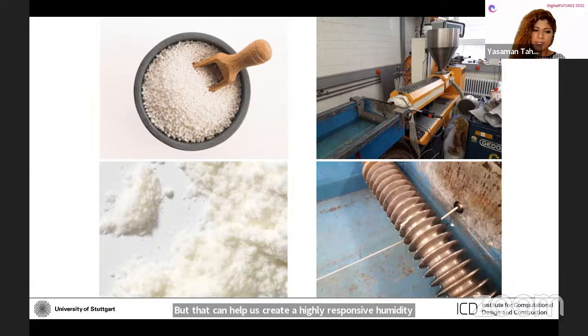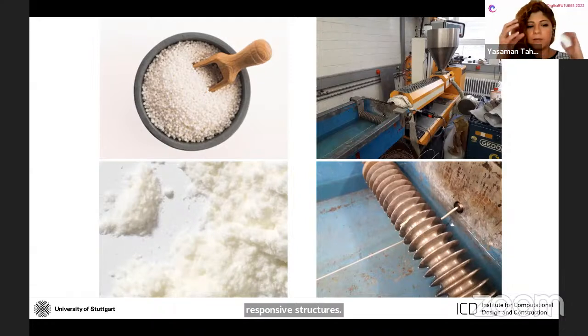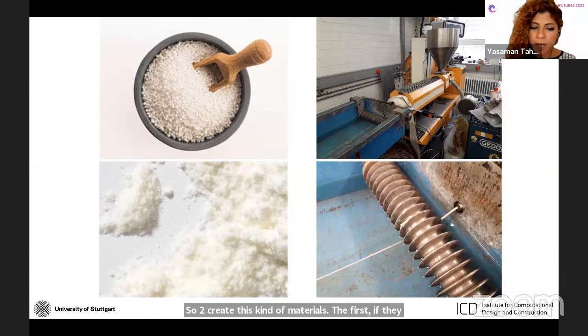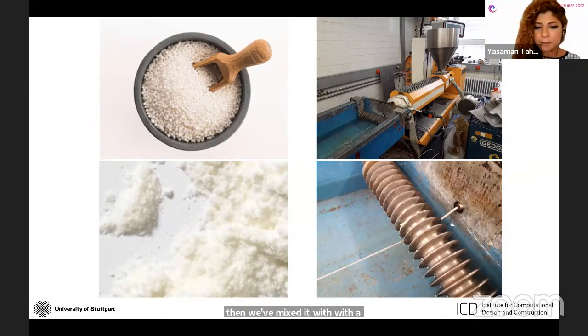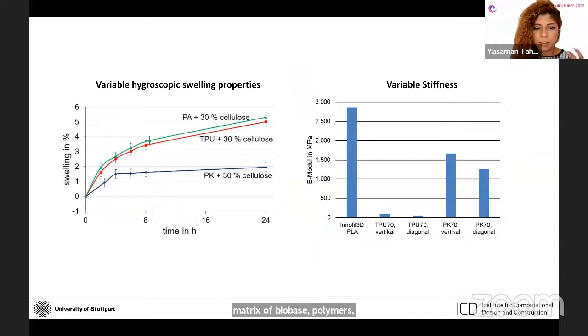So to create these kinds of materials, we looked at the basic elements. We looked at pure cellulose powder as the hygroscopic agent, and then we mixed it with a matrix of bio-based polymers. And since we could pick the percentages of each of the cellulose and the polymers, and we could also use different polymers, we could really define the properties of the materials that we were creating. Properties such as hygroscopicity, stiffness and flexibility.